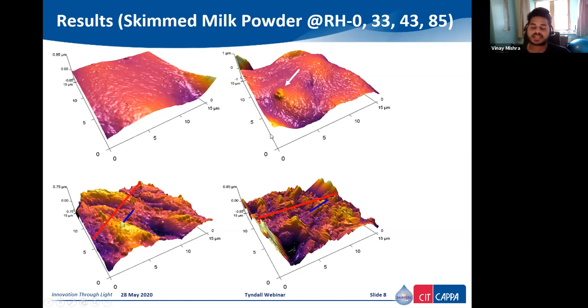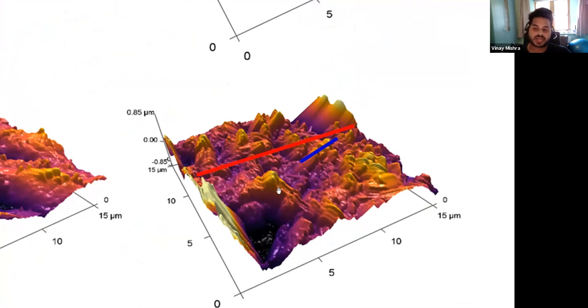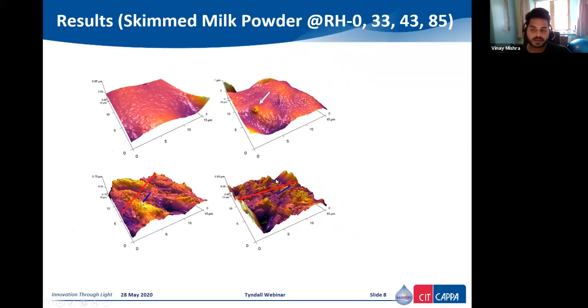Now, I wanted to mention here that SMP or skim milk powder has higher lactose content in it. Now, lactose remains in amorphous form if kept at a lower temperature and lower water activity. But as the moisture content increases, the amorphous form of lactose starts to change to crystalline structure, where you can clearly see there is a small nucleation or small peak development on the surface of skim milk powder. And you can see there are not very uniform, but everywhere small lactose peaks on the surface of skim milk powder at relative humidity 43. As we increase further, you can see that in SMP 85, skim milk powder 85, there is lactose crystallization stacking on the surface.